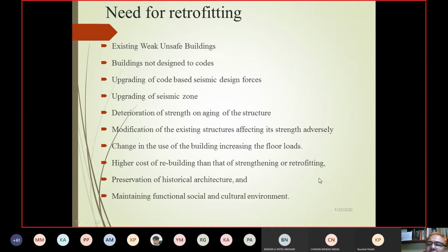In some areas also, in residential buildings, they are using embroidery machines and they start the embroidery machine, and the vibration will be a problem. Higher cost of rebuilding than the strengthening or retrofitting. Then preservation of historical architecture. This is a very costly affair, but we have to do it because we have to design the mortar for that particular historical architecture, because as the moderator said in the previous lecture, the compatibility between the repair material and the existing structure is a very important point. In this historical architecture, the existing structure is so old, and we have to design the mortar for this preservation.